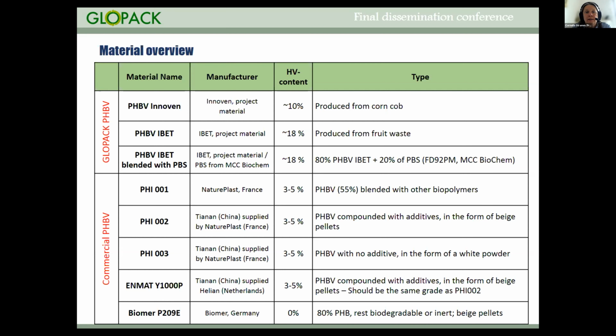We also carried out trials, and a lot of trials were carried out with commercial grades of PHBV. Here we used different suppliers, namely Natureplast and Helian. For example, the PHI002 and the ENMAT polymer type seem to be the same grade delivered from Tianan, from China, to the different suppliers, so that you have a better overview of which material we are working with. These grades all have HV contents around 3%. And one additional difference is the PHI003. This is a grade without additives and based on a powder. So here we start the process of compounding to get granules.